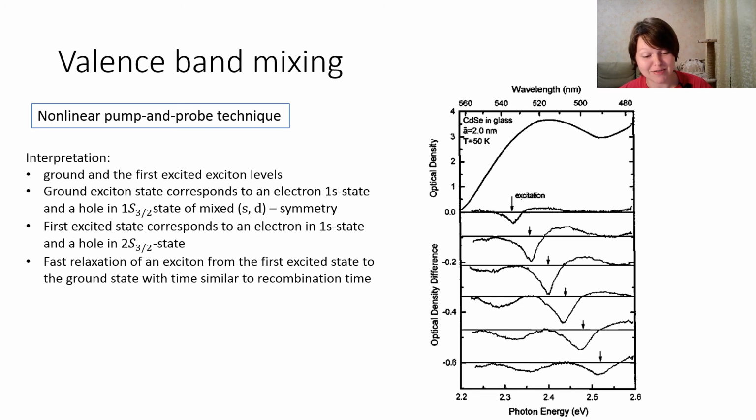In real nanocrystals, again, in real nanocrystals, the deviation of their properties from that of the ideal particle occurs. So it means that we should see the fine structure in the absorption band of such crystals, but again, inhomogeneous broadening interferes, and we can't see the fine structure. That's why the complicated structure of the first absorption feature can be performed by several means.